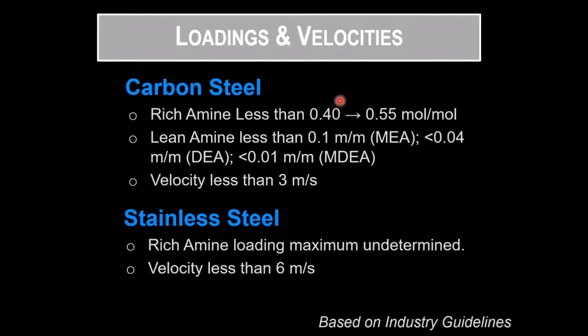As far as the rich side goes, between 0.4 and 0.55, why such a huge spread? The lowest part, the 0.4 or less, is generally related to CO2 facilities or processes that are primarily CO2 removal. Because of the absence of H2S to provide the protective film, we tend not to overload a solution with CO2 because it's a very aggressive corrodant. If we're treating primarily H2S, we can push that rich loading limit to 0.5 and potentially 0.55 mole per mole.